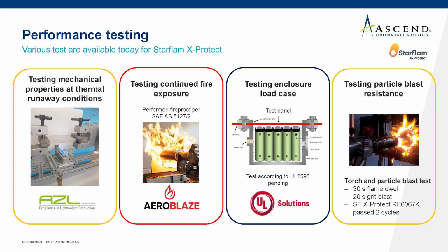We ran the UL2596 tests, only still need to review data and summarize the results, and we will gladly keep you updated in the future about that outcome. And we also ran a particle blast testing, known from some laboratories as torch and grit, for example. We managed to pass 2 entire cycles that consisted of 30 seconds flame dwell and 20 seconds grit blast.